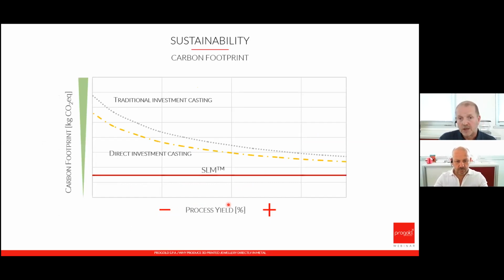From a sustainability point of view, SLM has a low and flat carbon footprint. We can see the low and flat carbon footprint regardless of process yield, while there is a higher carbon footprint for traditional investment or direct investment casting in case of low process yield. When later on the process yield increases a little bit, this value also goes through a drop.